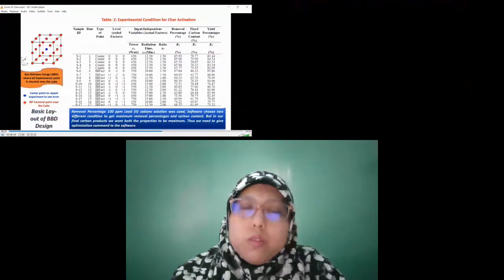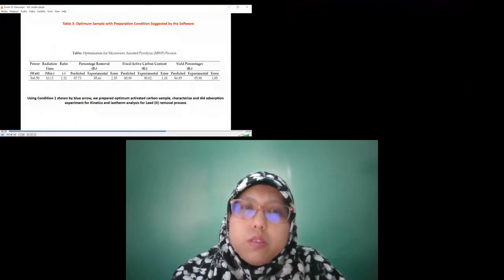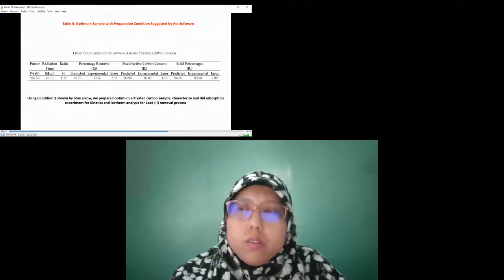If we consider this design matrix, we can see that sample number 6 has shown maximum removal percentage and fixed carbon, and sample number 11 has shown maximum yield percentage. So we have to optimize the process. This is the software-suggested optimization. We carried out this reaction, and we saw that our experimental result is slightly deviated from the one predicted by the software.